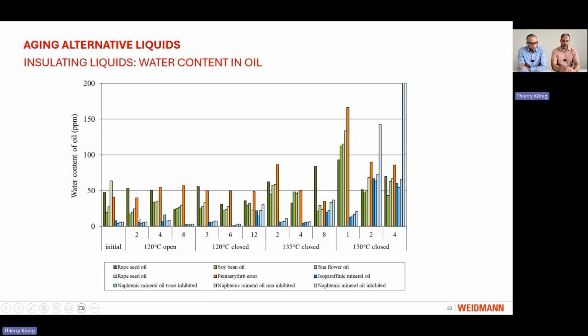For the water content in the ester liquids, hardly any impact can be seen, but here in the 135 degrees closed system and in the 150 degrees closed system, we see that at the first moment the water content in the esters increased, and after that it starts to decrease. Also here, more extreme at 150 degrees, it is higher in the beginning, and after that we see a decrease. The mineral oil in the closed system also increased over time.